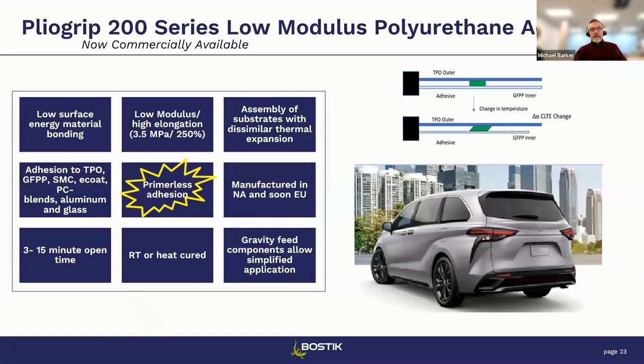Okay, so that brings us to the wrap-up slide here. We've got this Pliogrip 200 low modulus 2-component polyurethane adhesive, and these are the attributes that make it unique. It's been set up to bond these low energy surfaces without a primer, and this will minimize the amount of chemistries that you need to put into creating an assembly. It does need to be flame treated or plasma treated, but all of the commercial polyolefins today require some level of surface treatment, but we do not require a primer.